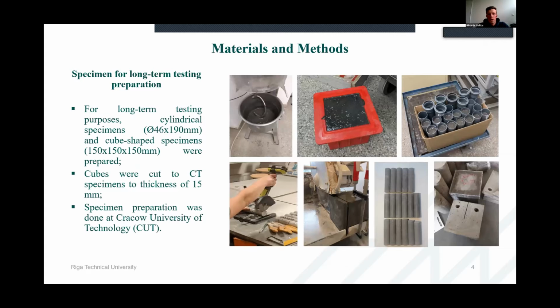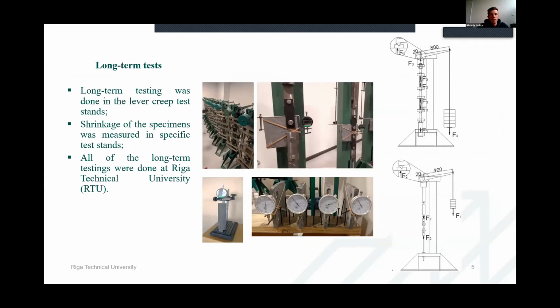So for the testing purposes, cylindrical and cube-shaped specimens were made. The cylinders were cut and ground to a height of 190 millimeters, and the cubes were cut into tile-shaped specimens with a thickness of 15 millimeters. I also have to mention that this was done at two scientific organizations, Riga Technical University and Krakow University of Technology. This part was done in Poland. So long-term tests took place in Riga Technical University.